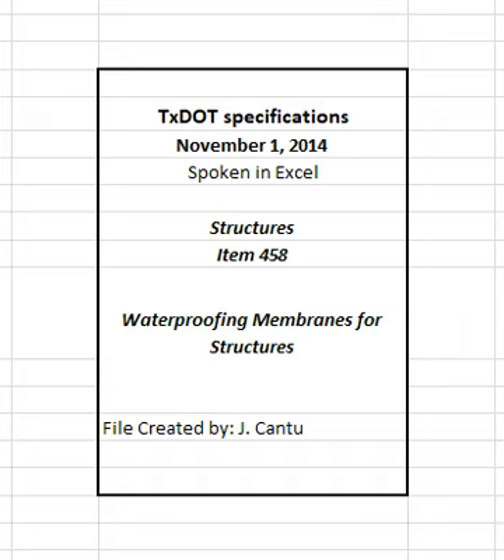3.8 Type RR1. Apply waterproofing to dry surfaces and only when the ambient temperature is above 50 degrees Fahrenheit. Ensure the butyl rubber or EPDM membrane is free from punctures, pockets, or folds. Turn the membrane into drainage castings without break. Take special care to make the waterproofing effective along the sides and ends of girders and at stiffeners, gussets, etc. Fill grooves with plastic cement.